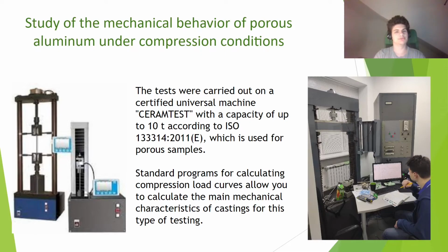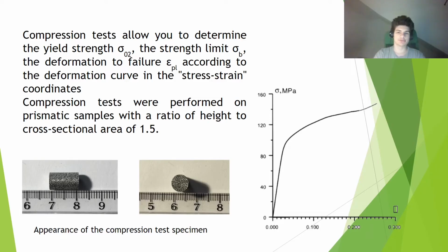Study of mechanical behavior of porous aluminum under compression conditions. The tests were carried out on a certified universal testing machine with a capacity of up to 10 tons according to ISO, which is used for porous samples. So here you can see the graph, and on this graph you can see the yield strength, the strength limit, and the deformation to failure. Compression tests were performed on prismatic samples with a ratio of height to cross-sectional area of 1.5.